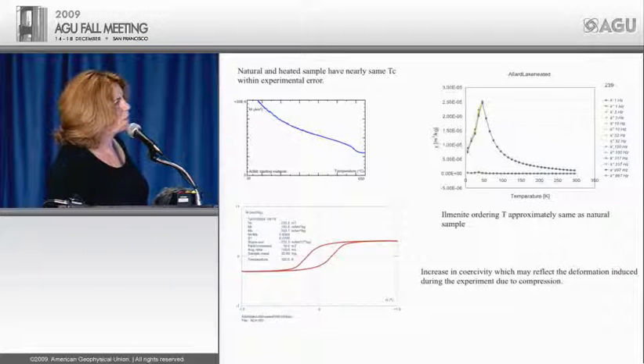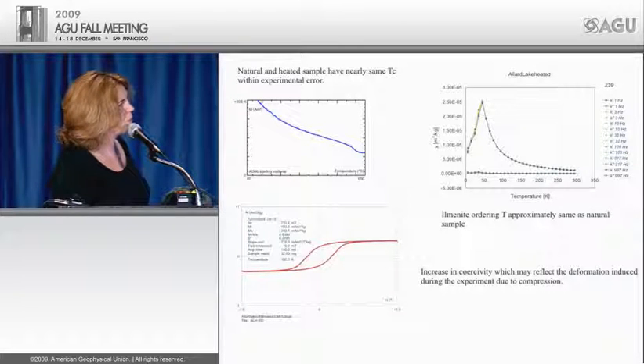We see very little difference in the susceptibility data with frequency. We see a little bit of difference here on this side, which I think might be a little bit of hematite going into the ilmenite there. And again, we see a little bit of change in the coercivity. We have a slight enhancement of coercivity.